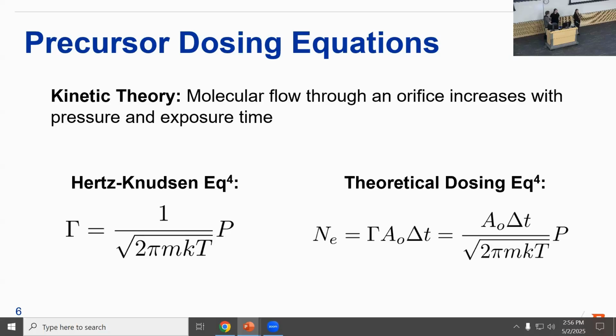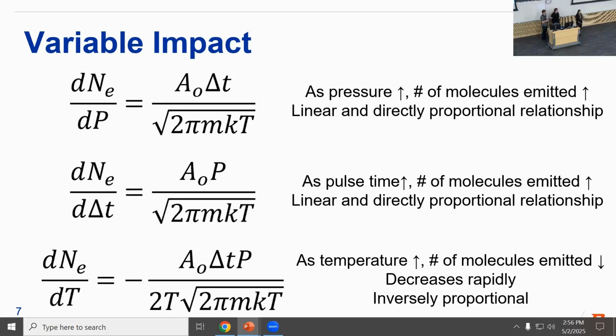So when an orifice of area A is open for a time T, you can then calculate the number of molecules emitted given by this precursor dosing equation on the right, where NE is the number of molecules emitted. And from this, you can see that the number of molecules is directly proportional to the cross-chamber pressure and the dose time. So by taking the partial derivatives of the precursor dosing equation with respect to the changing variables of pressure, time, and temperature, we can find out some relationships. For both pressure and time, as those variables increase, the number of molecules will also increase. The relationship is linear and directly proportional. However, for temperature, as temperature increases, the number of molecules decreases, and this will do so rapidly, and it is inversely proportional.